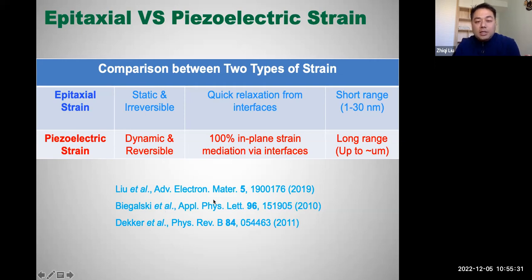Okay. And even for this APL work and the PRB work, their study was based on, I think, lanthanum nickel oxide superlattices, lanthanum nickel oxide, strontium titanium oxide, bismuth iron oxide. The authors grew this kind of oxide thin films on top of PMN-PT, and I think they performed depth-resolved XRD analysis. They found that the in-plane deformation of the top thin films is quite consistent with the substrate.